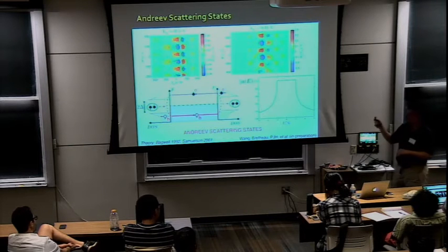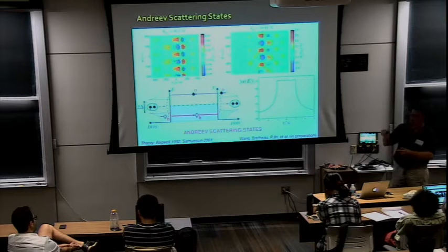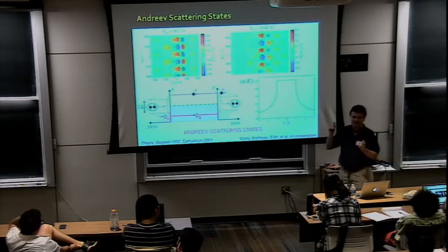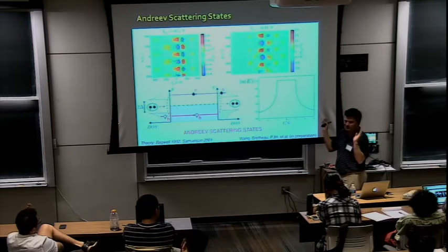It could be a different type of Fabry-Perot effect. The key thing is that we see something like a Fabry-Perot effect, but now it gets modulated with the phase difference according to the way it should be. That's what convinces you that it has to do with Andreev physics and not a geometrical Fabry-Perot, which has to do with something else. Okay? So it was the combination of having all the knobs available to identify it, I think. It could have been observed earlier.